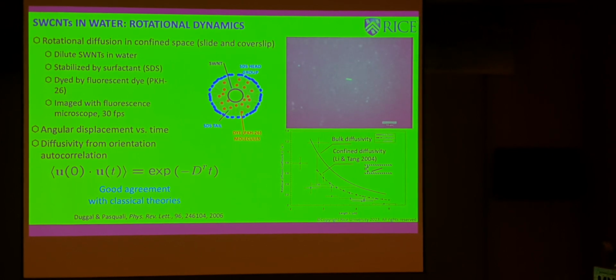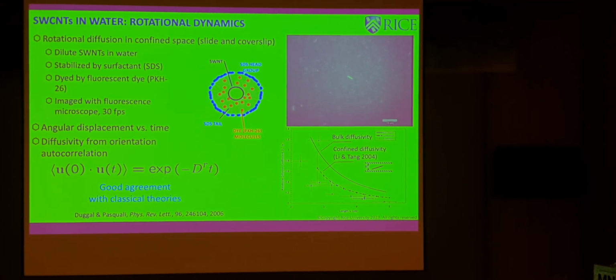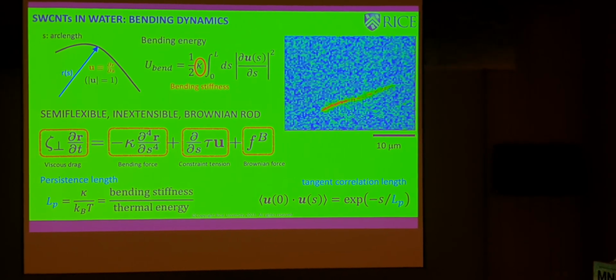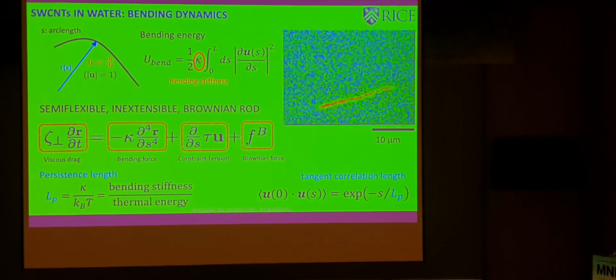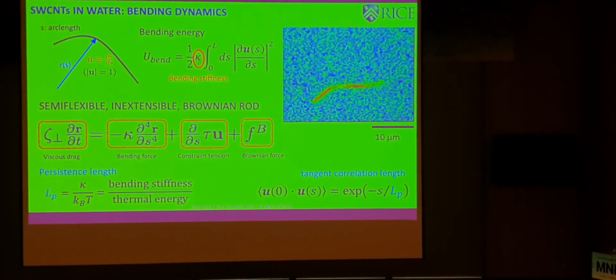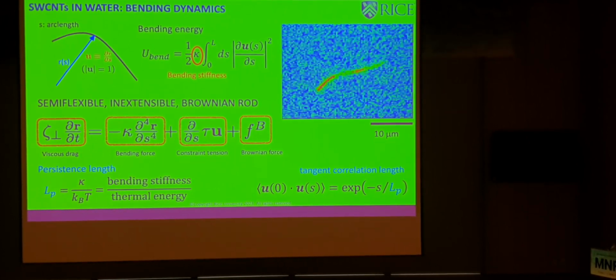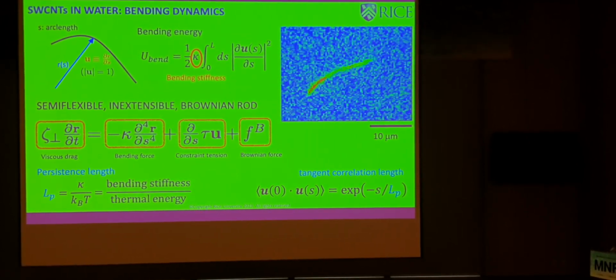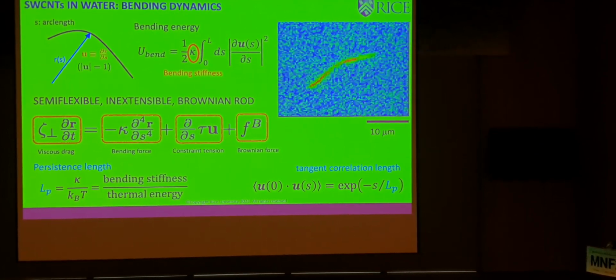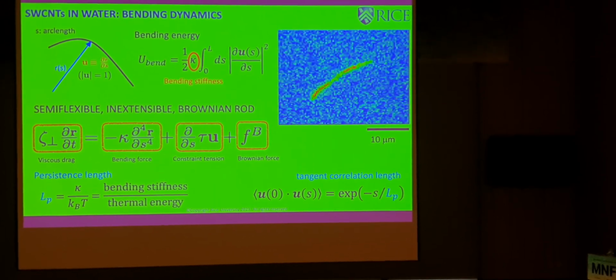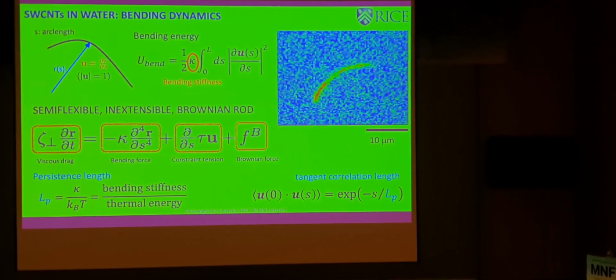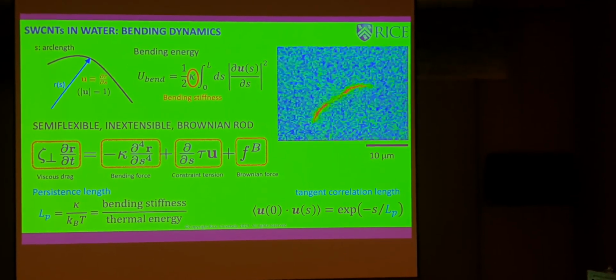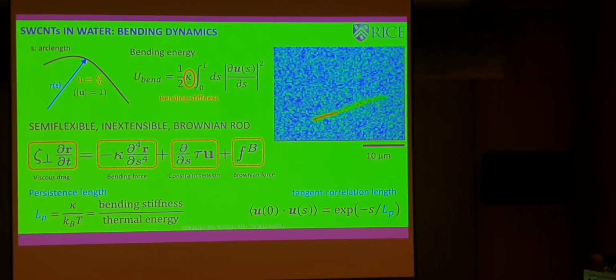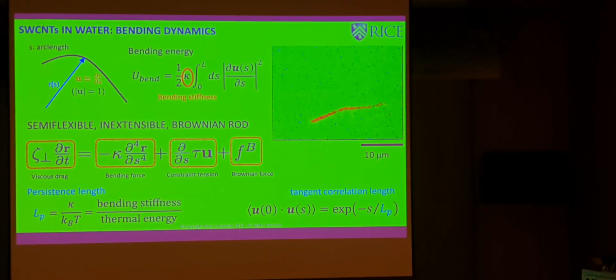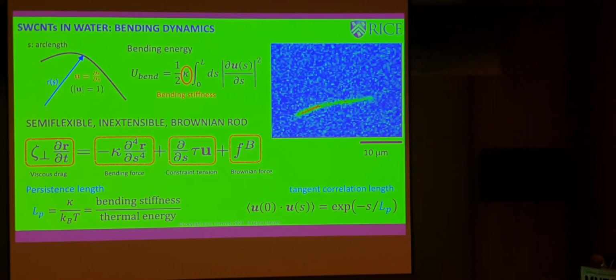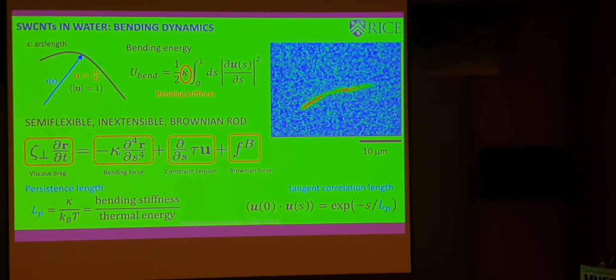You also notice that the longer ones actually fluctuate a little bit in shape. And if you go look for really long ones, so this is about 15 micron, you do see these shape fluctuations. And so you realize that, of course, like any material, they have a finite thickness. This was actually published in PNAS a long time ago, so I think the movies are online if you like them. So you can treat them as semi-flexible and inextensible Brownian rods, and you can measure the bending stiffness by looking at the persistence length, which is the ratio of the bending stiffness to kT, which is your thermal energy.